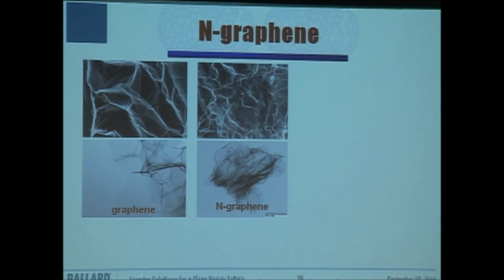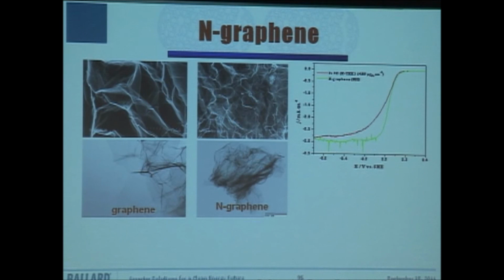Sorry. So for the same reason as carbon nanotube, we don't want to start with plain graphene because the interaction with metal is extremely difficult. We start with nitrogen-doped graphene. So in this case, we can maintain the same structure. However, I can get dispersion.